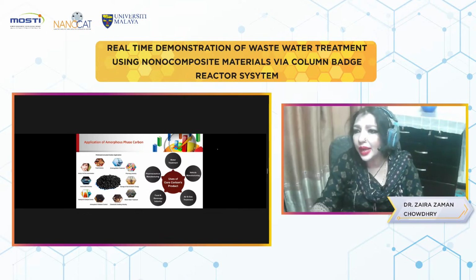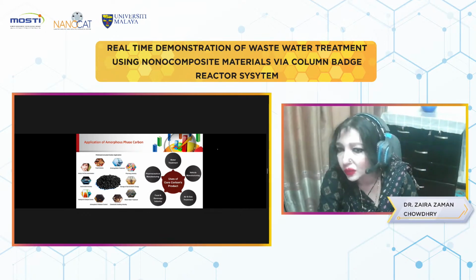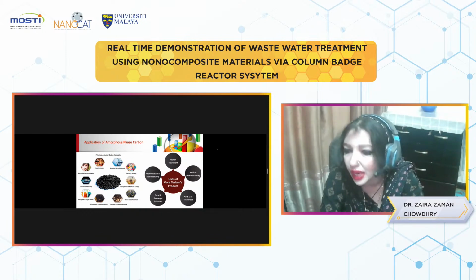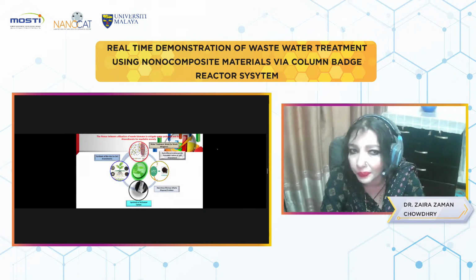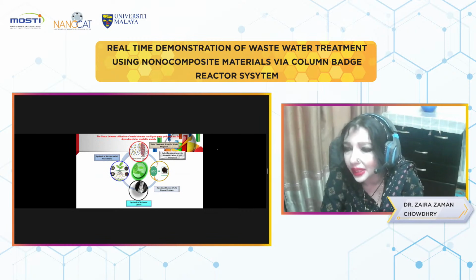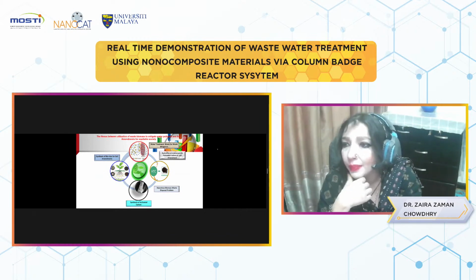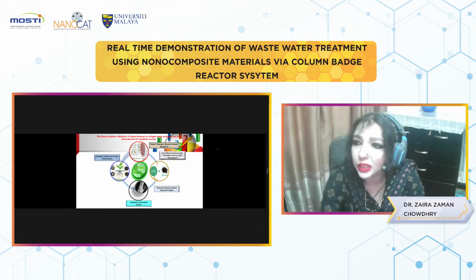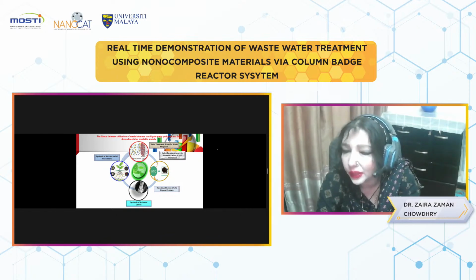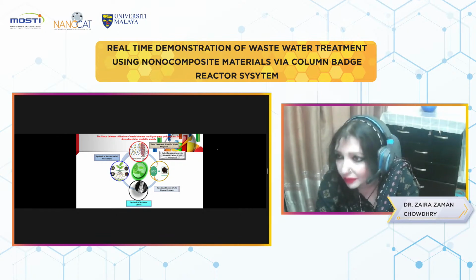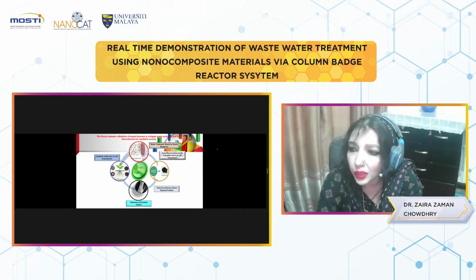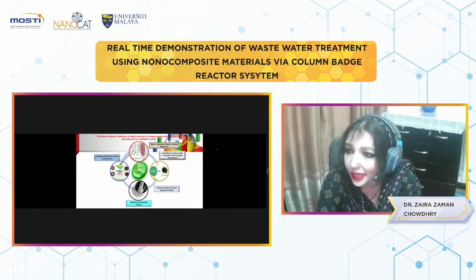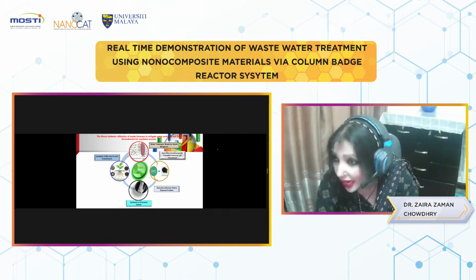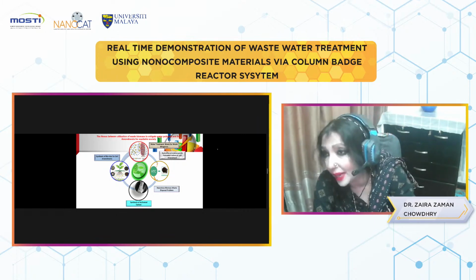Activated carbon until now has been used for water treatment, gas treatment, pharmaceutical manufacturing, food and beverages, air and gas treatment also. As I mentioned earlier, activated carbon, we can get biochar based on the temperature. In presence of nitrogen, if the temperature is within 400 degrees centigrade, the pyrolysis process will give us biochar from biomass. If the process is carried out in underwater at high pressure, only in 250 degrees centigrade or 200 degrees centigrade, we will get hydrochar. Since water is present, the term came hydro.